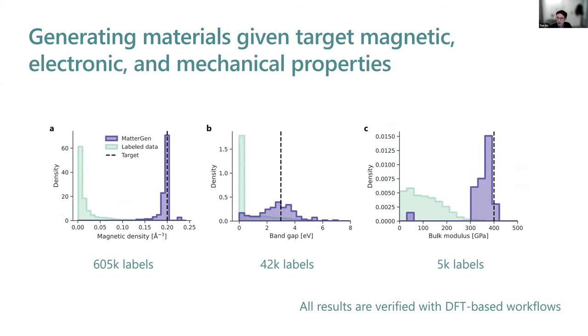So I think one key result that we get is that we show MatterGen can generate materials conditioned on a diverse range of property conditions, including magnetic density, band gap, and bulk modulus, including electronic and magnetic properties. Here, we fine-tune the model with different numbers of training data, as you can see listed here. But for all these three properties, you can see that we can bias the property of the generated distribution very far away from the original training data. Here, the purple is our generated distribution, and the green is the training data.